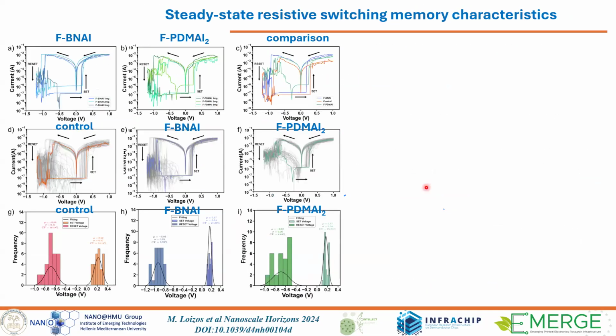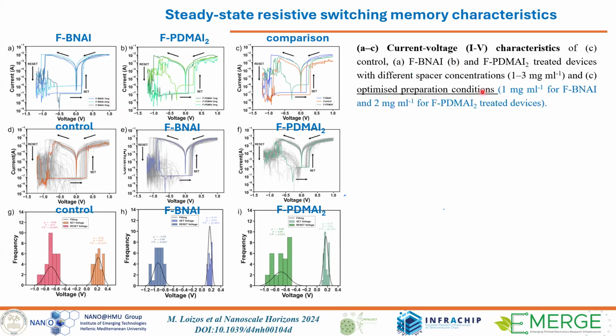Then we fabricated devices: reference devices, and of course devices with F-BNAI and with the second type, the PDMA 2D perovskite as a capping layer. And then we tuned the thickness of this capping layer through controlling the concentration of the solution that we deposit on top. And we found the best thickness for these two different capping layers.